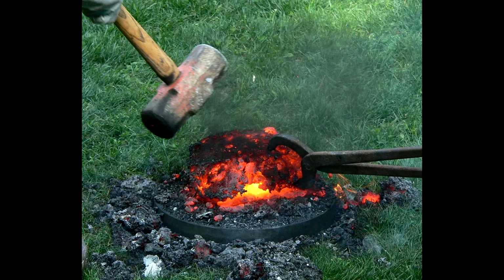Even with all of that effort, with fluxes and using tongs or a frame to carefully consolidate our bloom, we're going to end up with a lot less mass from slag ejection and oxidation than we started with. Sim and Ridge, original citation, estimate that the final mass of the billet consolidated from the bloom might be about half of the mass of the original bloom we worked to last time. But there would have been wide variance, and no doubt skilled bloomsmiths would have done much better than inexperienced ones. It is worth noting that while any blacksmith likely could work bloom into a billet, this job tended to be done by specialist bloomsmiths, likely working close to the smelting operation, rather than generalist blacksmiths.